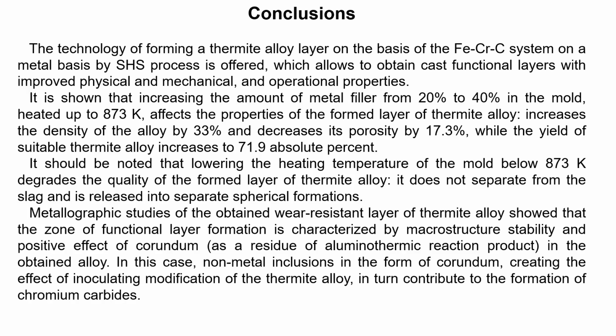It should be noted that lowering the heating temperature of the mold below 873 kelvins degrades the quality of the formed thermite alloy layer, which doesn't separate from the slag and is released into separate spherical formations.